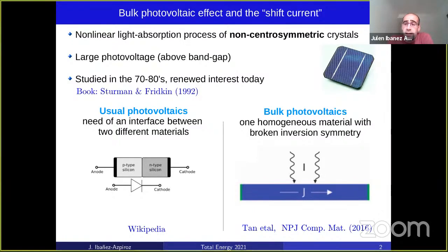Now, one of the main characteristics of this effect is that it can conduct a photocurrent in a homogeneous material. If we think of usual photovoltaics, one needs an interface like a PN junction in order to generate an internal electric field that will drive the photoexcited electrons. But in a bulk photovoltaic, this is done automatically by the material. So the role of the interface, in some sense, is done now by the broken inversion symmetry of the material that allows it to conduct electrons along certain directions.